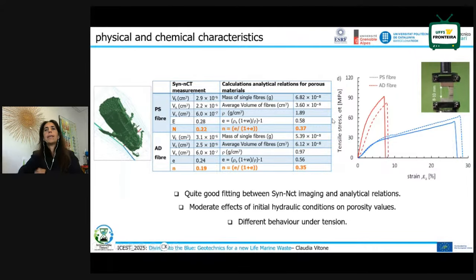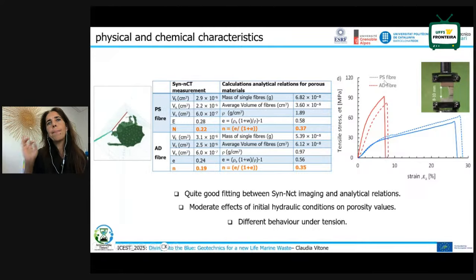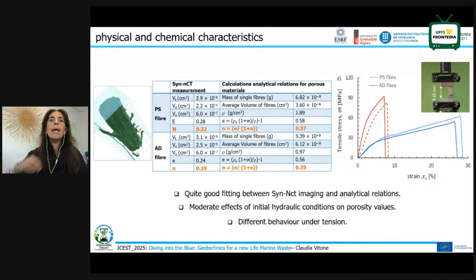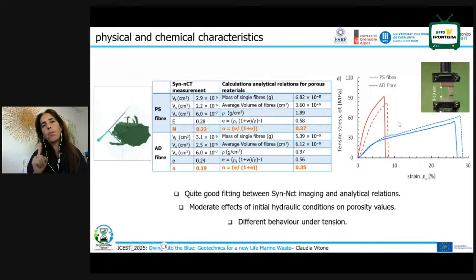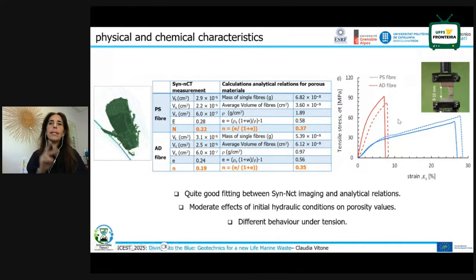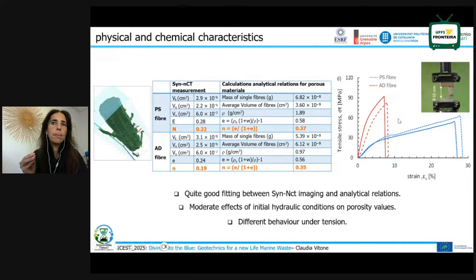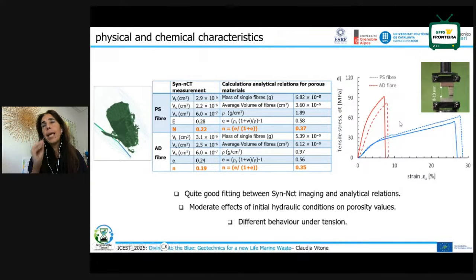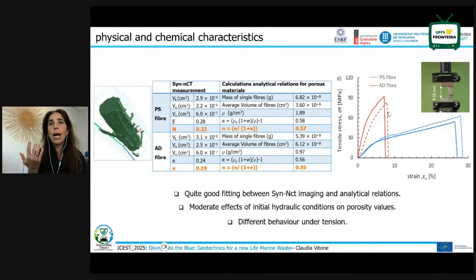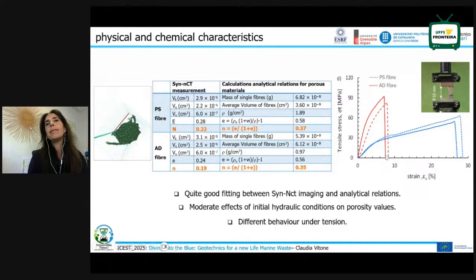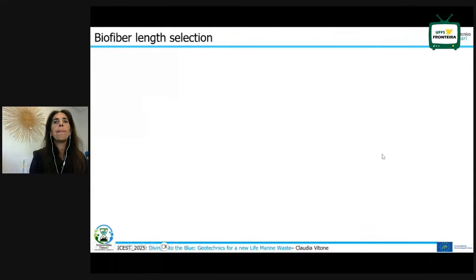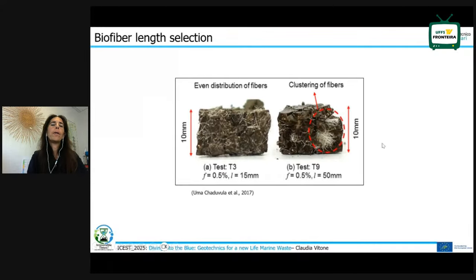Then we have in the two conditions, so for just pre-soaked fibers and just air-dried fibers, we could perform some tensile tests. As you can see here, irrespective of what we have seen in the synchrotron, where essentially the images and the porosity are similar, the behavior under tension of the single fiber is very different, because if the fiber is air dried, the tensile stress is much higher than the pre-soaked fiber, and the elongation is much lower.